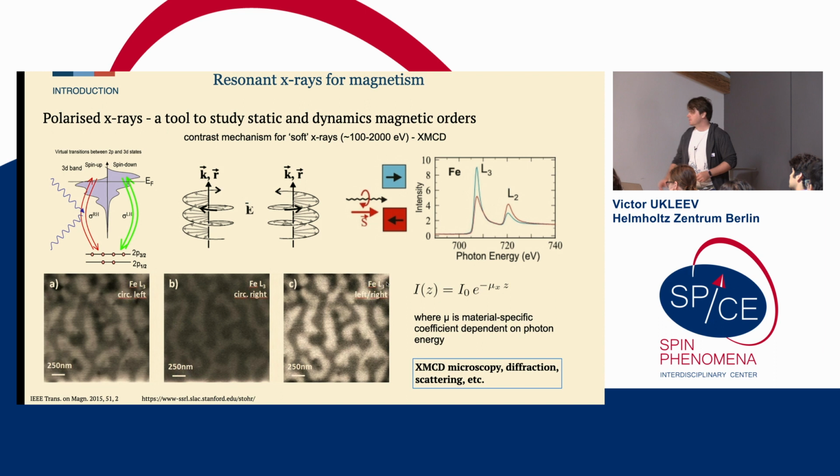And if you can focus the X-ray beam and scan your piece of iron with left and right circularly polarized X-rays, you will see the magnetically dependent contrast. That's because the absorption coefficient for left and right polarizations will be different, and if you take a difference or divide one by the other, you can even enhance this magnetic contrast and see the magnetic domains.